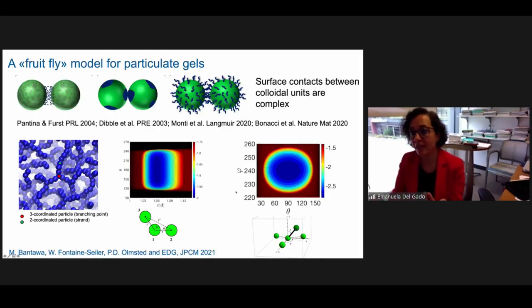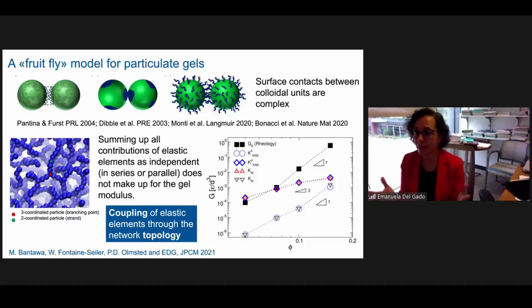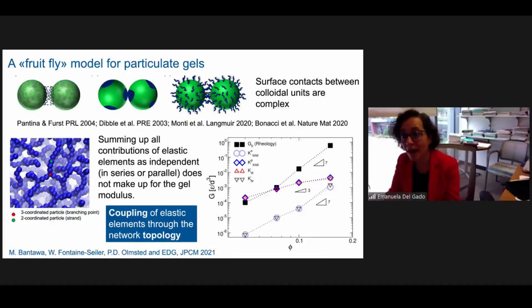So once that we have the expressions for this elastic energy cost, now we can compute the modulus that we would predict for the gel if we consider just adding up all these structural elements as if they would contribute independently to the elasticity. And then we can do other simulations, and we can basically perform rheological tests on our gel as it is there and obtain the modulus from that. So in this plot, the empty symbols are basically the modulus that result from adding up these different structural elements in the statistics in which they are present in our gel network, but where each elastic contribution is computed independently from each other.